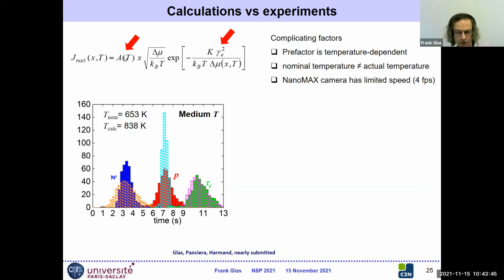Complicating fact is that the prefactor is temperature dependent, but very annoyingly, we have a nominal temperature for the experiments in the NanoMAX, but I convinced myself that this nominal temperature is much lower than the actual temperature. Not going to go into details, but we don't actually know the temperature. So each temperature at which we perform an experiment is actually an extra fit parameter. So we have many fit parameters.